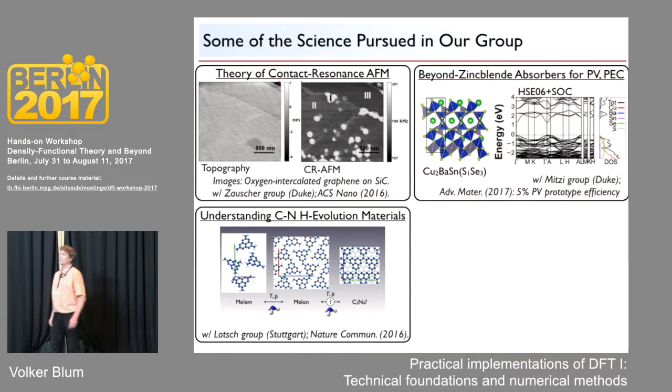It's a so-called graphitic carbon nitride, or C3N4. Because it's a 2-dimensional material, it almost looks like graphene. There's many, probably well over 1,000 publications studying the properties of this material. We did some ab initio thermodynamics that Matthias also briefly introduced in his talk to see under which conditions this material is actually stable. And it turns out that according to our ab initio thermodynamics, this material is in fact not stable under any common synthesis conditions.